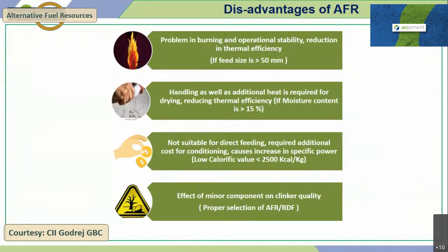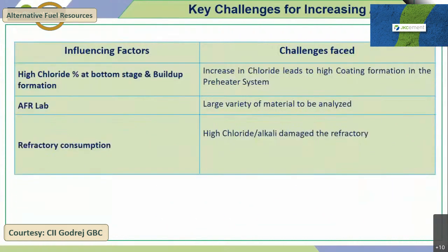These are the disadvantages of AFR. We face problems in burning and operational stability when the feed size is larger. Handling moist material increases the additional heat required for drying. And direct feeding is not suitable; some treatment is required before feeding this material. And sometimes the minor elements available in AFR impact the clinker quality. These are the major challenges everyone faces when using AFR.